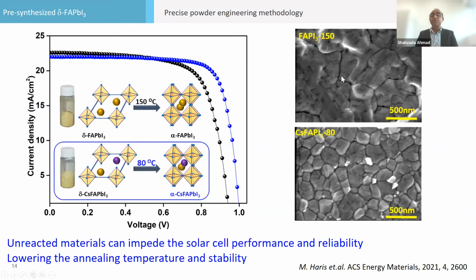And this is the crystal also at 80 degrees. You can see it's very pretty, not a very large size, but a regular size of crystal. So by doing the powder methodology, I think all the unreacted lead can be dissolved here, and solar cell performance, and especially the reliability, will be better.